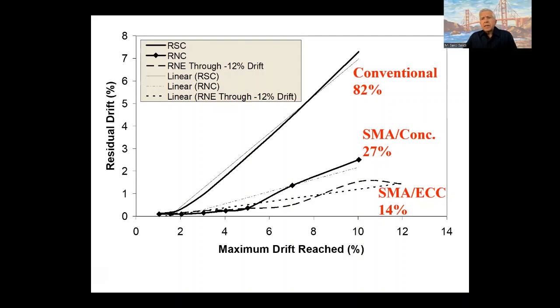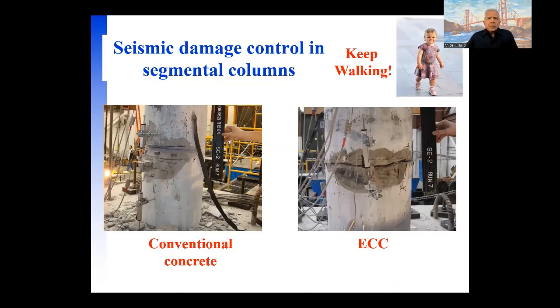When we combine SMA and ECC, we notice that residual drift drops by a factor of 6. This is about 1/6 of the conventional column. But the one that has SMA and no ECC is somewhere in between. Still, shape memory alloy brings the column back, but the fact that we didn't have ECC in that column still contributed indirectly to residual drift. In other words, ECC was the solution here. We kept walking.